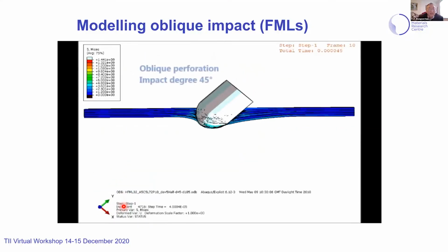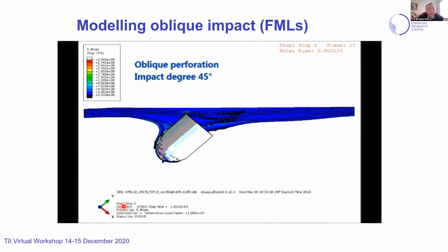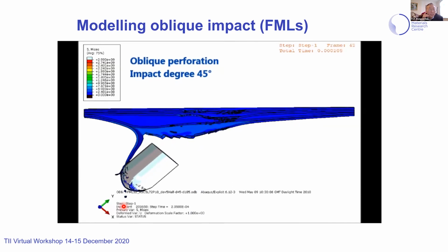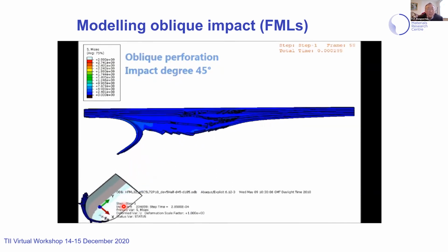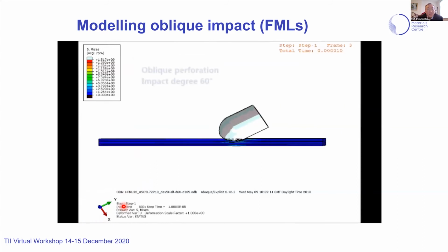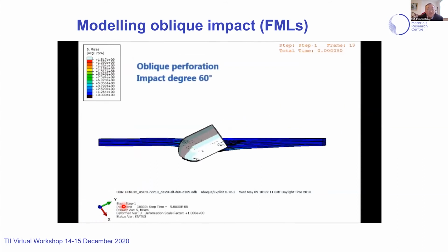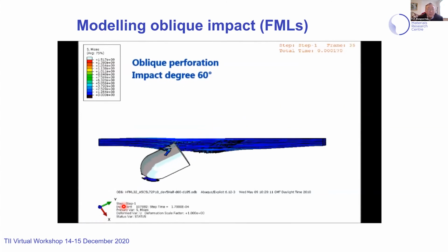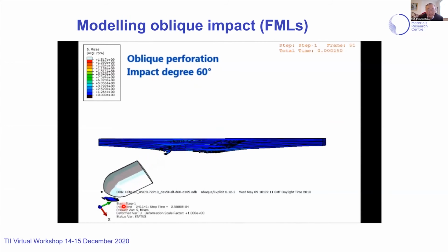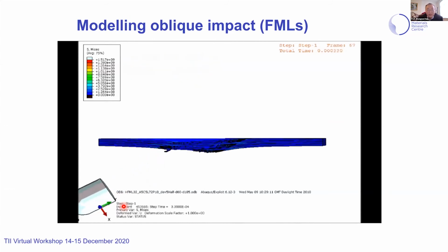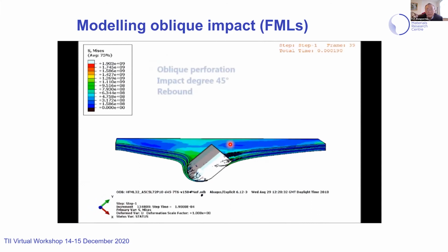And then we have 45-degree. And the final one is 60-degree. So this is very shallow. So if you get lower than that, or higher than that, you get a problem. Yeah, so you cannot get fully perforated.